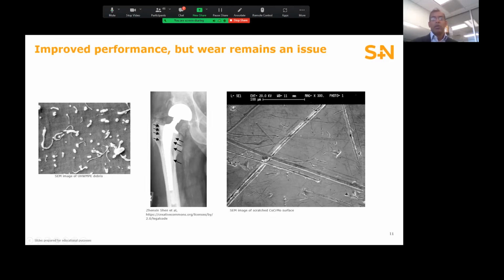Another observation that occurred as the devices were revised was that some cobalt chrome heads exhibited scratching, and this was likely caused by bone chips or bone cement debris. The presence of these scratches prompted concerns that wear could be accelerated. So while the utilization of polyethylene with cobalt chrome heads was a large step forward in hip replacement and greatly improved longevity, there remained room for improvement, and wear-related concerns remained at the forefront.